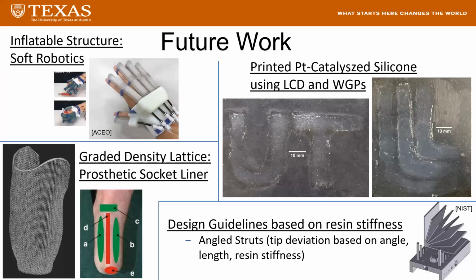So in addition to curing acrylate resins, we have also had some success curing the platinum catalyzed silicones that I discussed as the motivation for our work. That's seen at the top right, and the UT and Livermore logos were cured with an intensity of about 80 milliwatts per centimeter squared for 20 seconds, which is about 2 orders of magnitude higher flux than commercial resins typically need to cure. So curing these parts would raise the temperature of the LCD screen even after we replace the film polarizers with wire grid polarizers. It still raised the temperature of the screen to about 80 degrees Celsius.